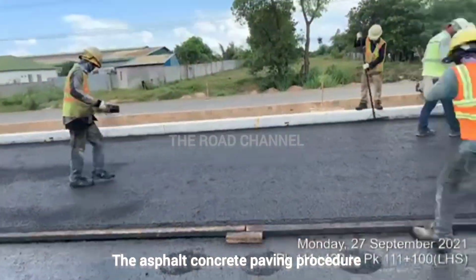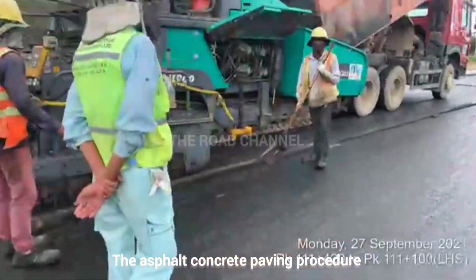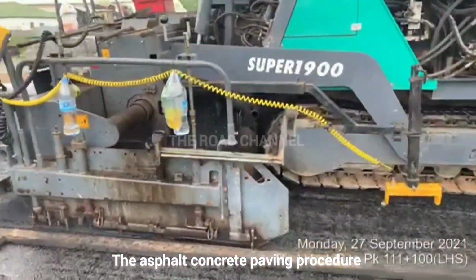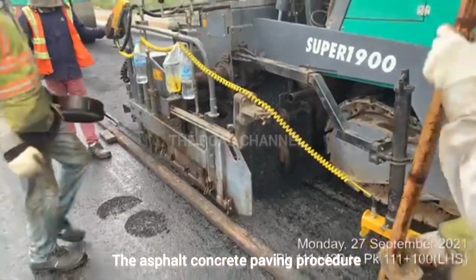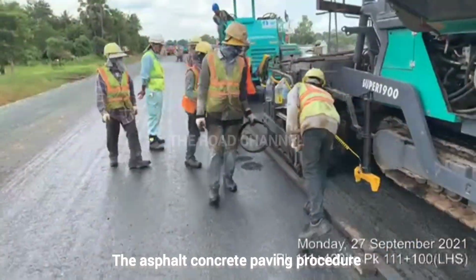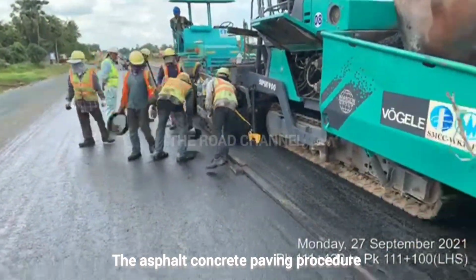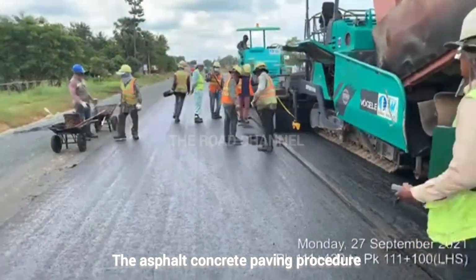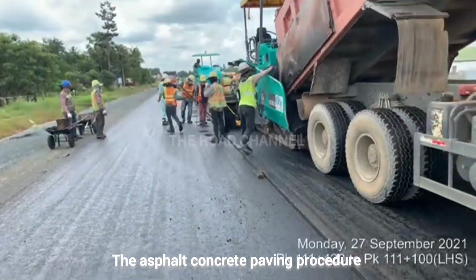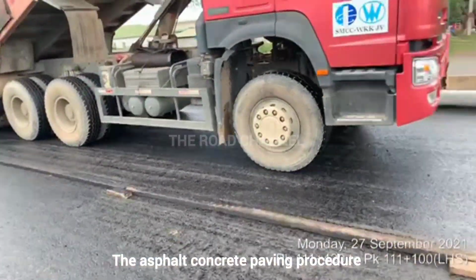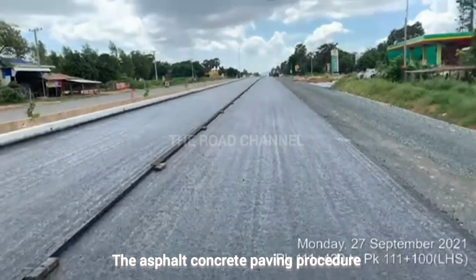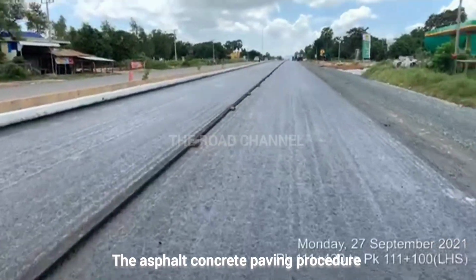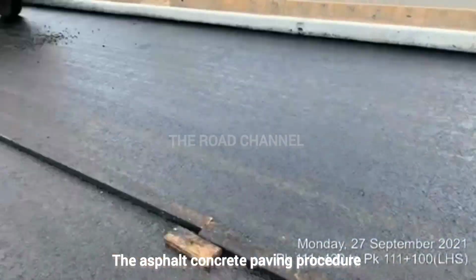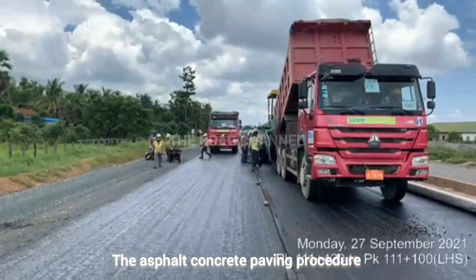5. Post-paving checks. Surface smoothness. Use a straight edge or laser profiler to check for bumps or depressions. Maximum allowable deviation is typically 3 to 5 millimeters over 3 meters. Joint quality. Ensure longitudinal and transverse joints are properly compacted and staggered. Avoid open or weak joints that can lead to premature failure.